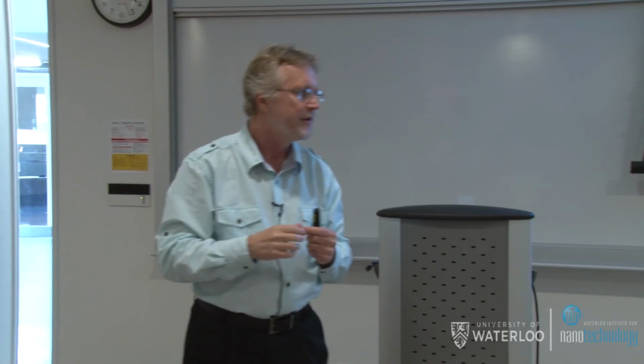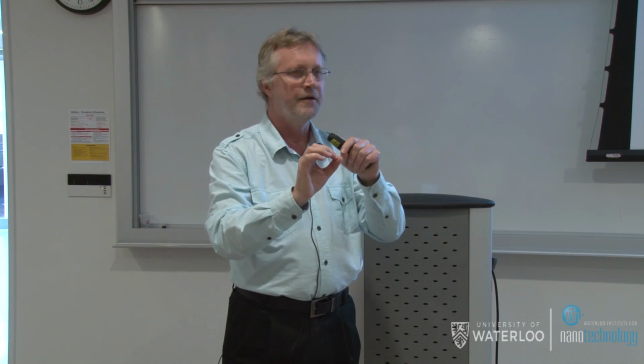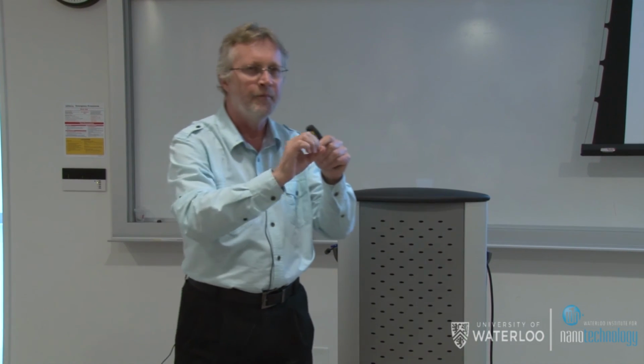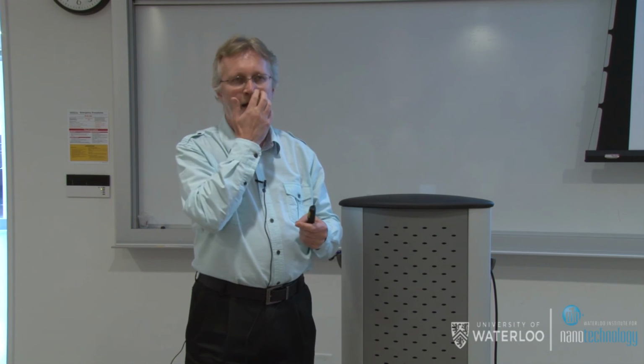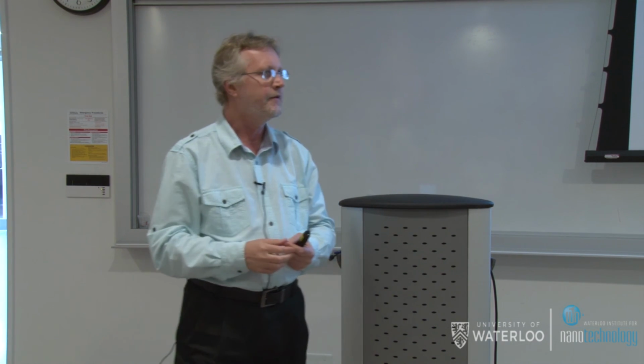And it's really amazing. I just don't understand why people didn't pick up on it, because basically there are 2 groups who are studying those. And we put in carbon nanotubes, because in the center you have to have a defect, and the defects add to the energy. So the material would be happy to take a single wall nanotube, which is a few nanometers, and get rid of the defects. And we indeed find that you can put in nanotubes, and then the conductivity changes by orders of magnitude. So you can play with those things. We just started working with adding nanoparticles to these materials. Quite interesting, I guess.